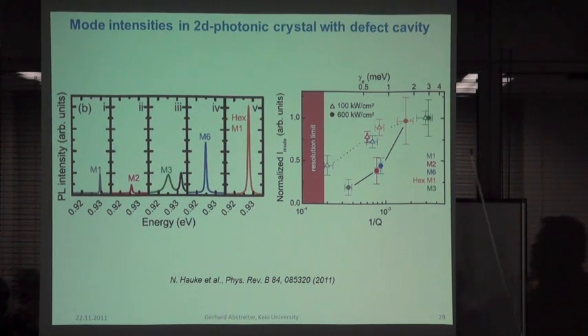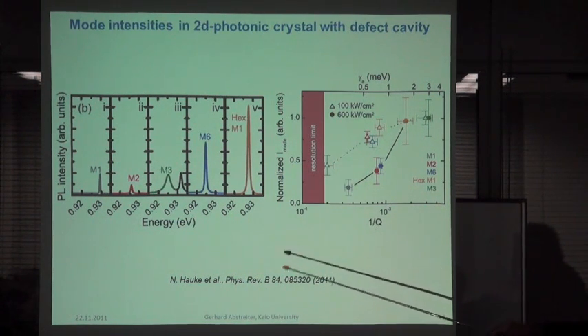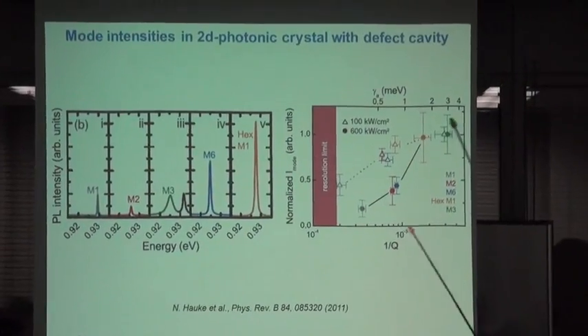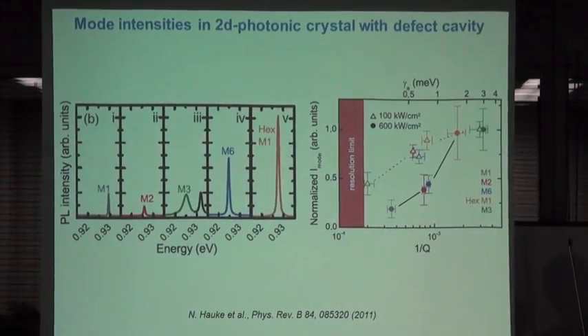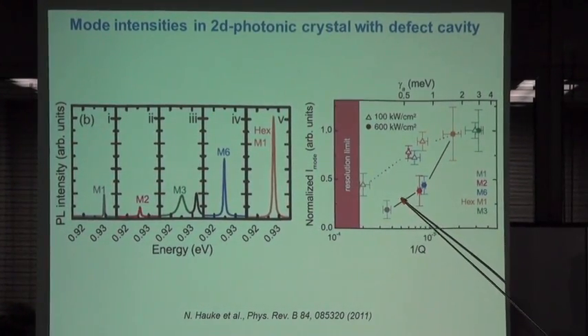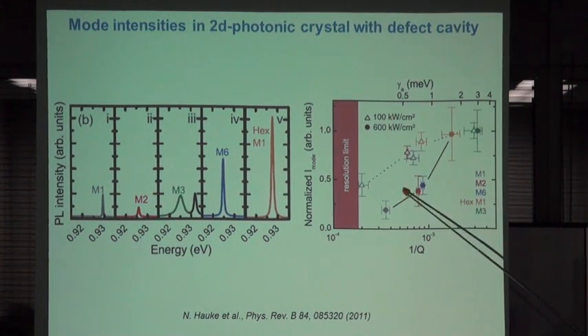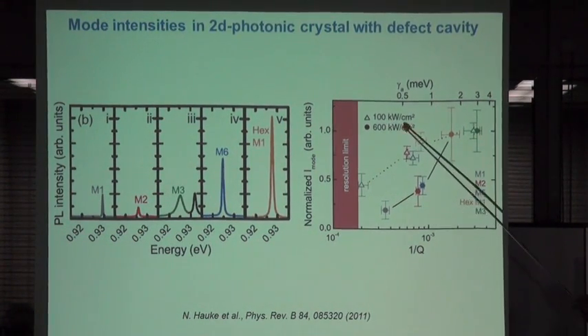And this has to do with the fact that if I couple a high Q cavity to an oscillator which has a lower Q, then you get most of the intensity when the Q is not so good and it overlaps with the oscillator. So if you want to just get light out, too high Q finally goes down in intensity. And we did a detailed theory, and also when you change the excitation power, you see a dependence. This is due to free carrier excitation and free carrier absorption.